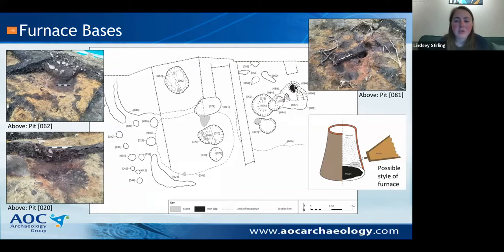So each of the furnace pits appeared to have at least one central circular pit that we reckon was probably where the furnace itself sat. They contained slag, charcoal and burnt clay, and there was probably a higher concentration of iron-rich slag and more burnt clay coming from these parts of the features. So these pits were likely used for the collection of the iron bloom during the smelting process. And the circular shape that you see would have been where this ceramic chimney-like structure would have sat above.